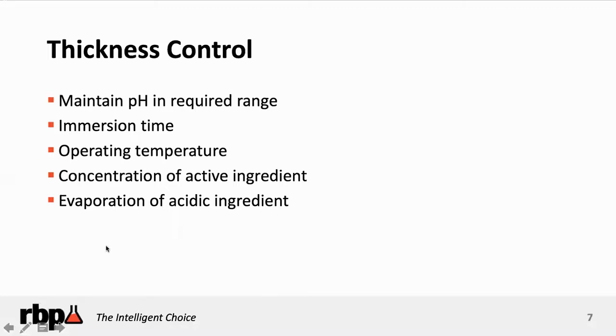Now, regardless of what OSP you pick, whether it's the thin versus thick, there are several things you should ask. Number one, you've got to control the thickness. So there are several areas in process control that are critical. One is to maintain the pH in the required range. pH is important because that allows the coating to form uniformly and in the proper thickness. With most OSPs, if the pH is too low, the coating will be very thin. If it's too high, it can be excessively thick. And that's not good either. So again, keep pH in the required range depending on the process you're using.